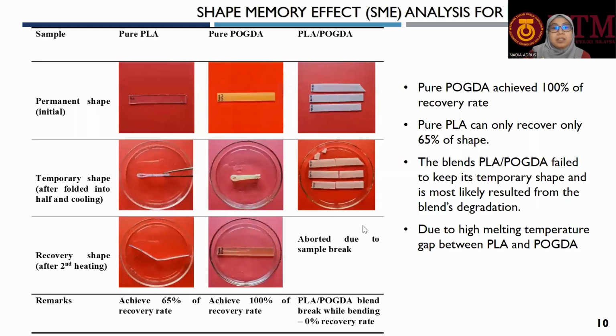So here are the results on the shape recovery of the pure PLA, pure POGDA, and also the blend. From this one, we can see that this is the permanent or initial shape, and this is the temporary shape after being folded in half and cooled. Here we see the recovered shape after second heating. Pure POGDA achieves 100% recovery rate from our calculation. Pure PLA can only recover 65% of shape. So that means our developed POGDA has higher shape recovery than pure PLA.